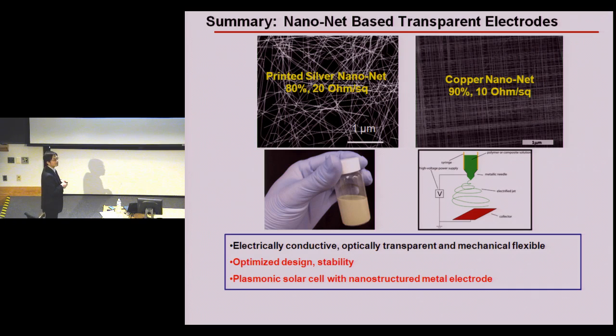Why should it be scattering at such a much smaller wavelength? Why should it scatter? Because the simulation shows you that it's much smaller than the wavelength, but we still get a certain level of scattering. That's why we only get 10% scattering instead of a much larger percentage of scattering.